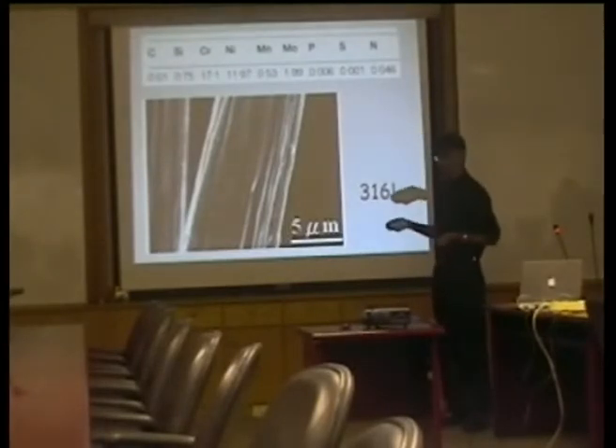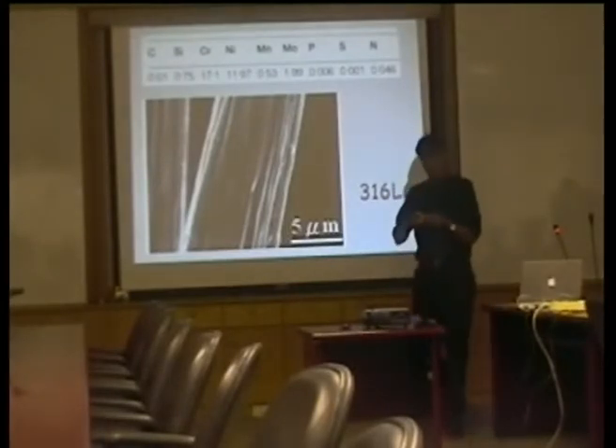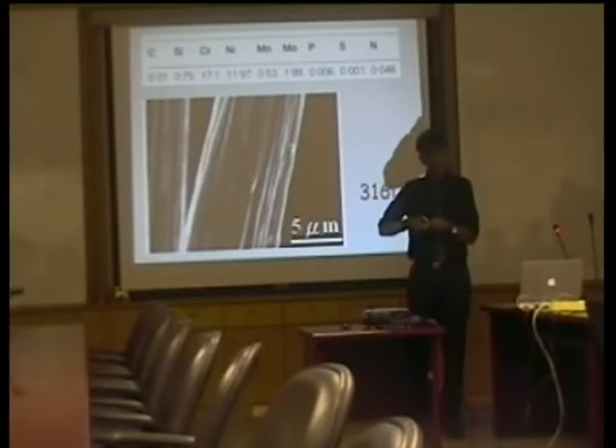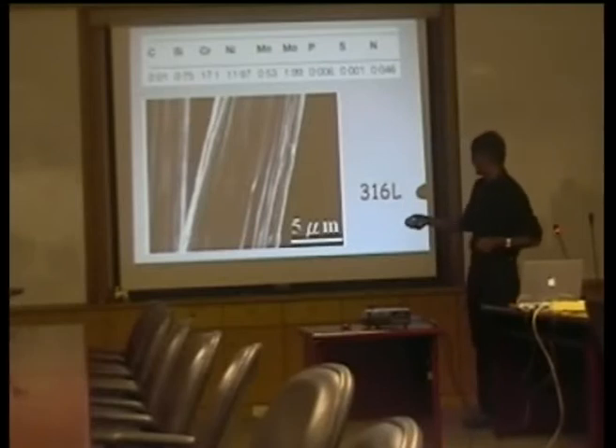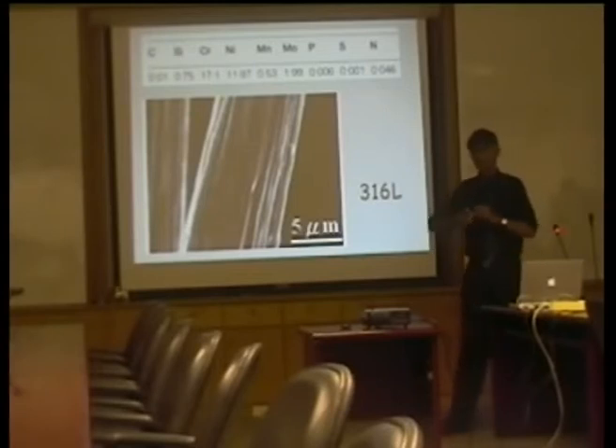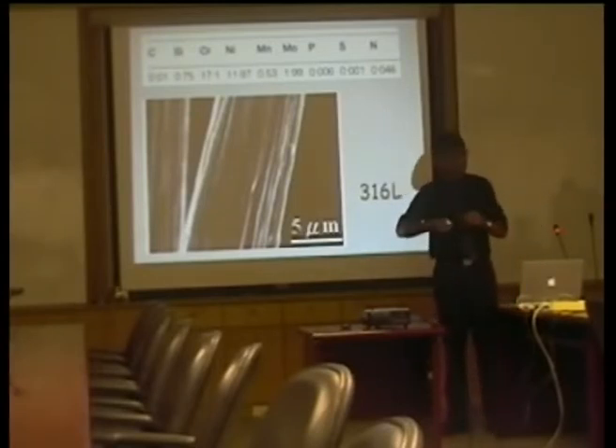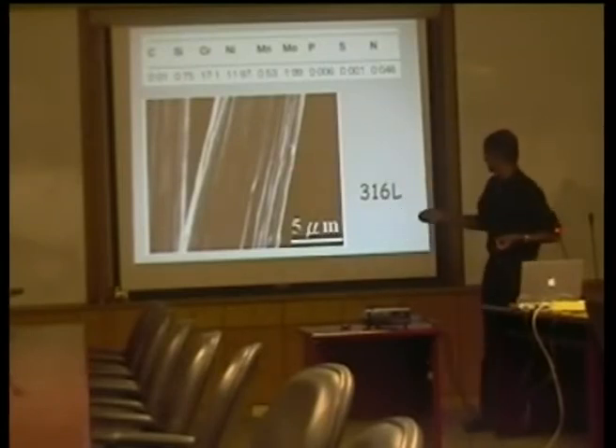If you look at it at high magnification, it's made by deforming 316L stainless steel. And this is one strand of the wire, so it's approximately 8 micrometers wide. And the detail that you see here is simply the scratches that exist in the die when you do the drawing. Okay, so this is just one single thread of stainless steel wire.